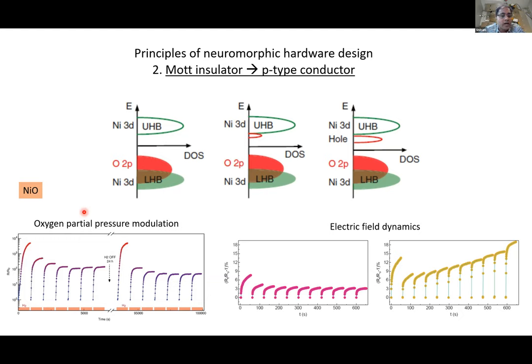Now, if you introduce air, that is, if you stop flowing hydrogen, the resistance will drop back slowly to the original value. And if you don't let it quite relax back to the original value, but you go back and forth, do the same exposure, you're basically training the material, or interval training. And you can create an out of equilibrium scenario here and demonstrate something called learning or habituation. So you have the same stimulus being presented, but the response is gradually decreasing.